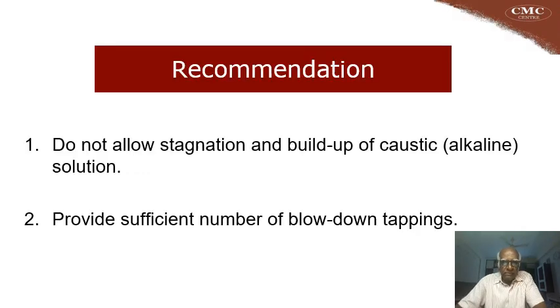So, recommendation. Any case study should end up in a recommendation. Diagnosis means stating the root cause of the problem. Recommendation means how to avoid such problem in the future. So in this case, it is a design fault. So we should not allow stagnation and buildup of caustic solution within the boiler, anywhere on the boiler. In this case, it has built up on the bottommost. That is why the tubes failed in the bottommost position. So in that position, we should provide sufficient number of blowdown tappings. So this is the recommendation for this failure.